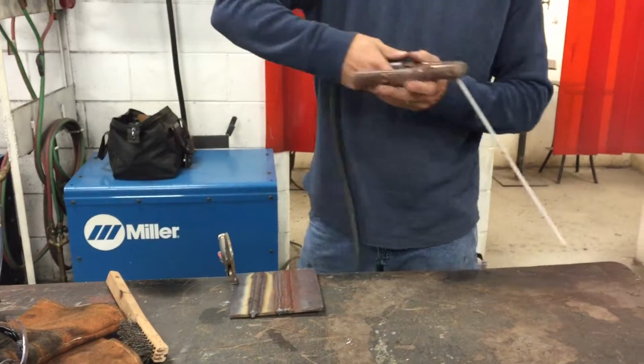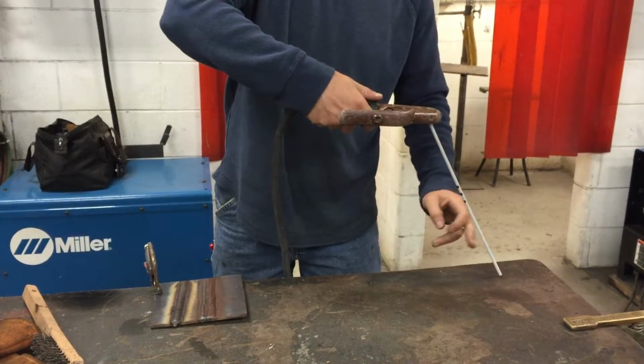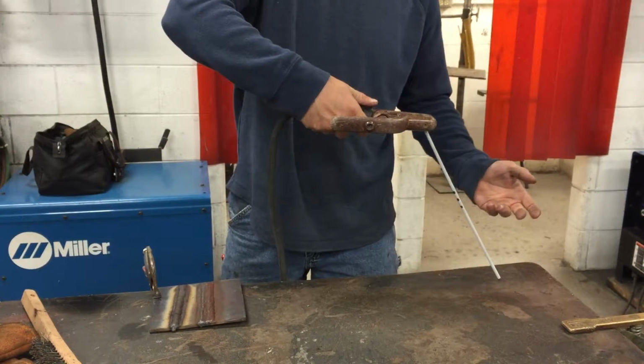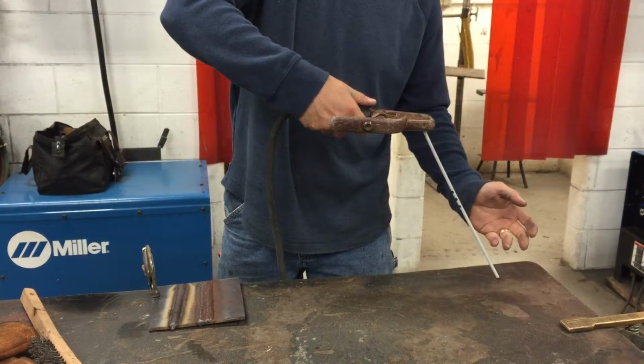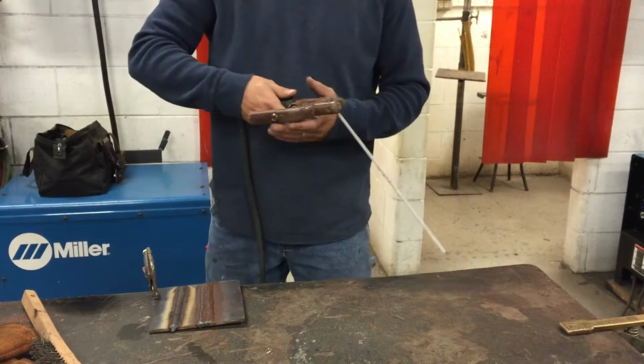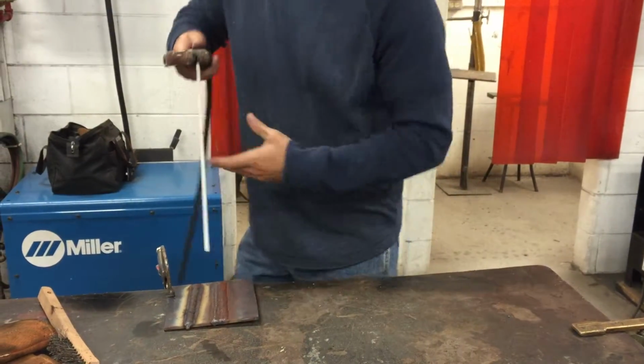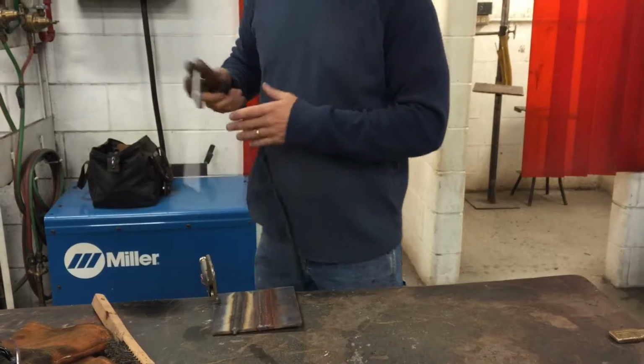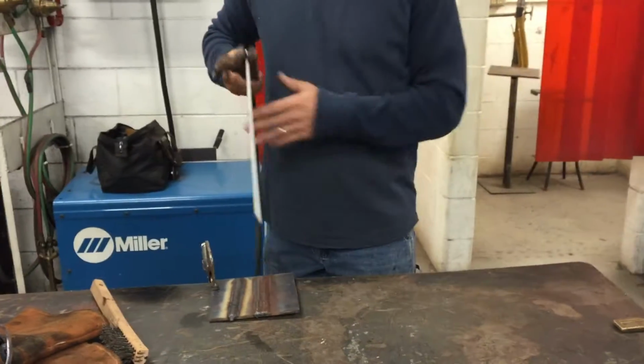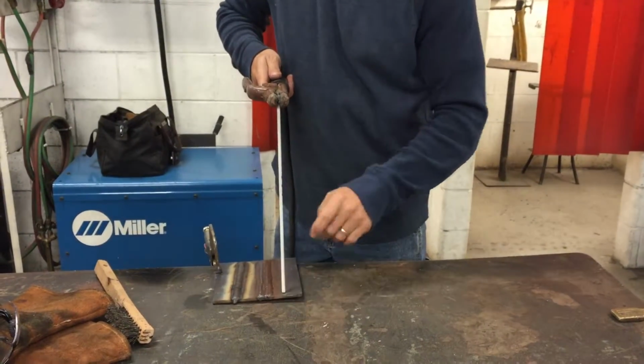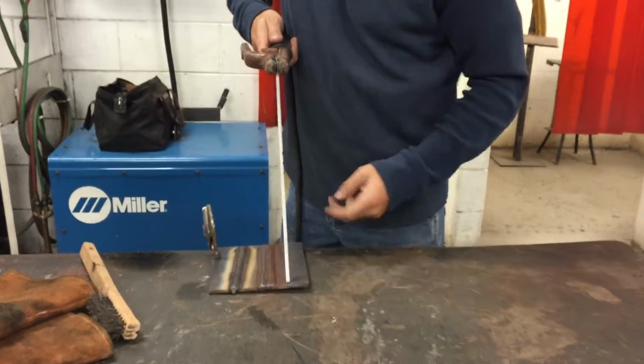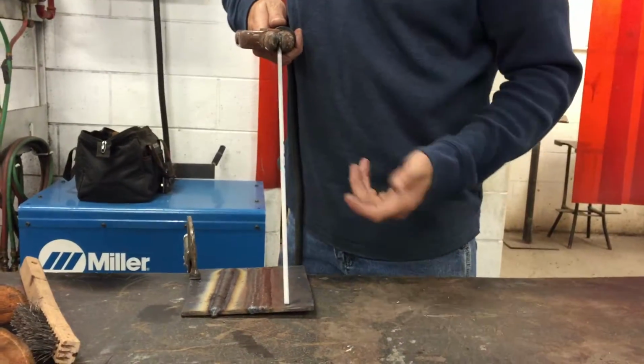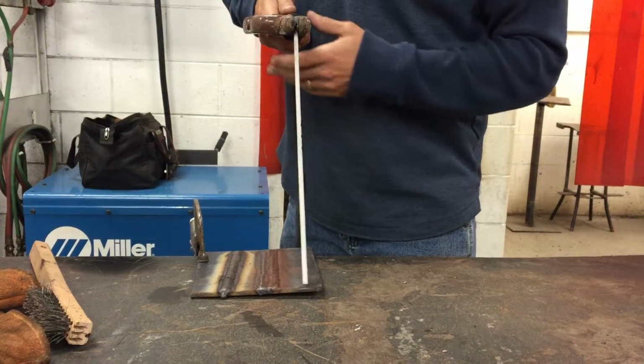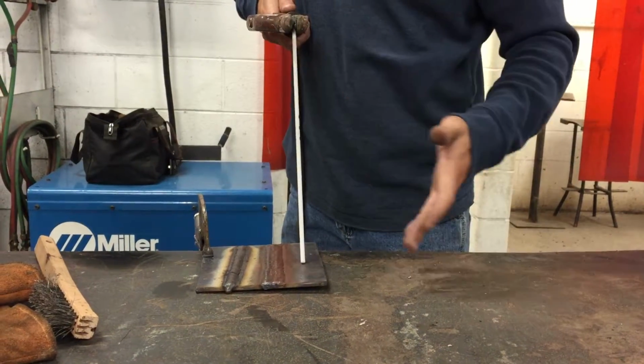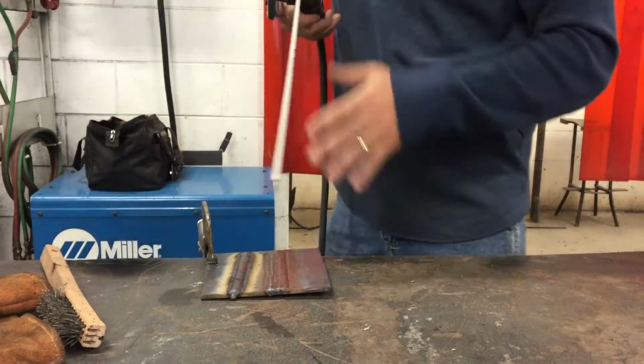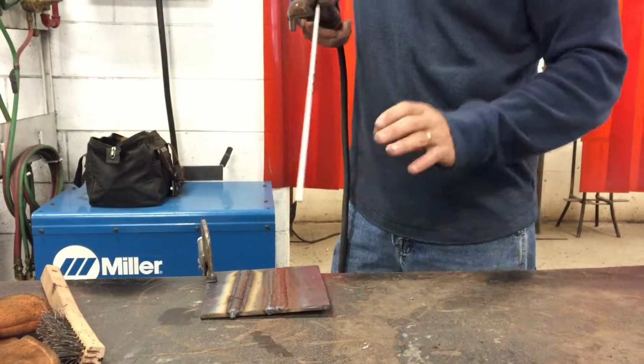Now that we know what our travel angle should be, which is somewhere between 75 and 65 degrees, or if you look at it another way, 15 to 25. So what you'll do then is on your first weld, your welder's turned on, you strike your arc. If you'll notice, my welding rod is at, if you measured, 90 degrees on both sides. You're going to run your bead continuously down through here. And the whole time, this welding rod is going to be consumed.